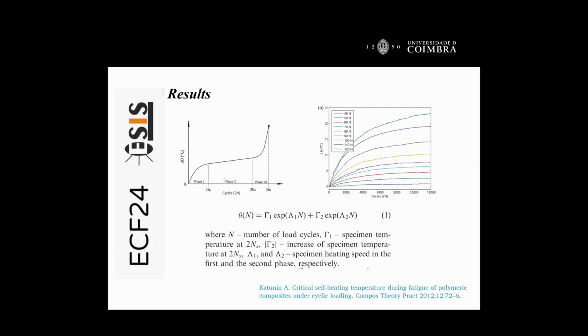What we want to do is find the critical point related to the critical self-heating temperature. It is here at this point. To obtain this point, because what we know is that the number of cycles to failure is the final point, what we want to know is how much this temperature is. And this evolution can be governed by equation 1. Equation 1 relates the number of cycles, the specimen temperature for a specific number of cycles, the increase of the temperature, and the specimen heating speed.